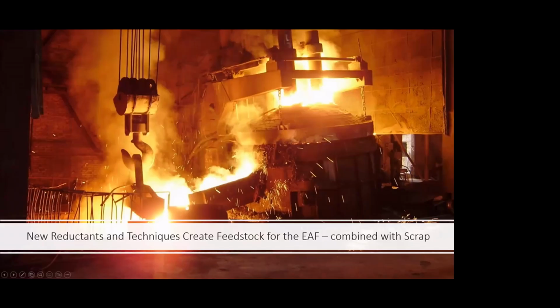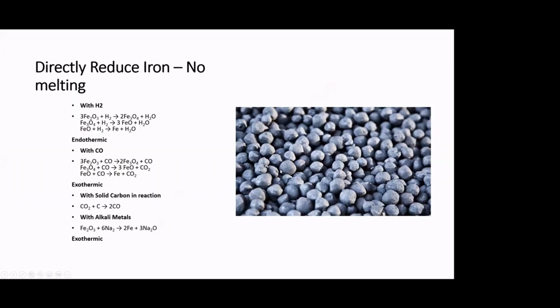So the other option is new reductants and techniques, and most of these materials are for additions to the arc furnace. I chose an old photograph of an arc furnace which looks a bit more like what I'm used to, fairly dirty, gassy, noisy, and this is potentially the future of green steelmaking. So the feedstock would be directly reduced iron. That means it's not melted and it's turned into metallic iron at below 1,000 degrees. Now this could be with hydrogen, but the really important thing to notice with hydrogen is that that's an endothermic reaction. So you have to heat the hydrogen, you have to heat the pellets in order to drive that reaction.